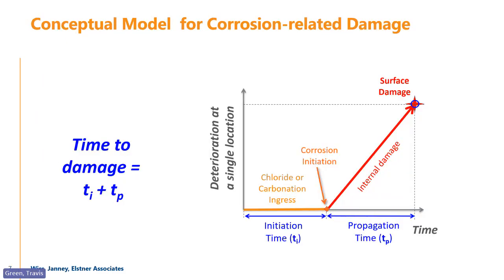So what are the basics, right? So really it's about, and I'm going to talk mostly in terms of chloride infiltration, right? Because that's what drives most of the concrete related, corrosion related damage in concrete structures in this area, right? So we have basically chloride diffusion. We apply chlorides to the surface in general, right? They diffuse through the concrete. At some point you get to a corrosion threshold, right? The concentration of the chlorides is so high that you initiate corrosion at the surface of the bar.